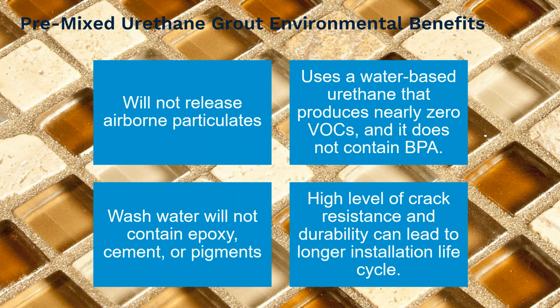Pre-mixed urethane grout has a lot of environmental benefits as well. Because it is not a powder, it will not release airborne particles. It uses a water-based urethane that produces 0 VOCs and does not contain that BPA. Wash water, so when you wash it as you go, will not contain any epoxy, cement, or pigments that you may find in a cementitious grout. And it has that high level of crack resistance and durability, which leads to that longer life cycle we talked about earlier in the presentation.